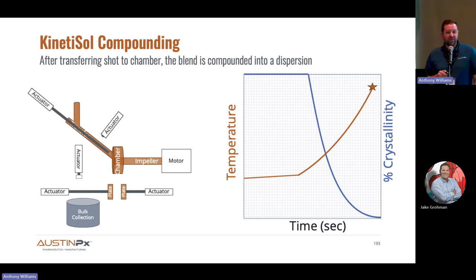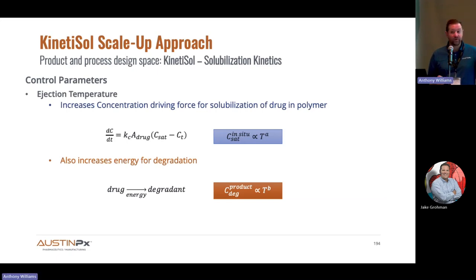But really, we can't measure the exact temperature of the dispersion directly. You can't do that in extrusion either. This is an apparent temperature. So what we're doing effectively for the process is generating a correlation between this temperature and the dissolution process that's occurring in the system. And so this is what happens inside the chamber after the material has been actuated into the machine. And we can talk about what's happening in the chamber in very complicated ways.